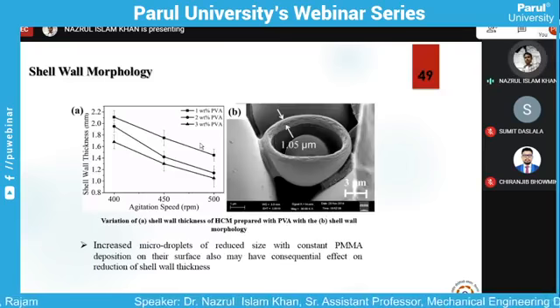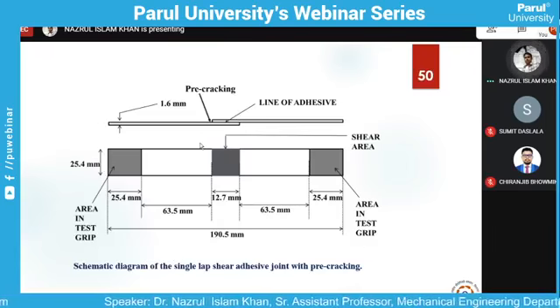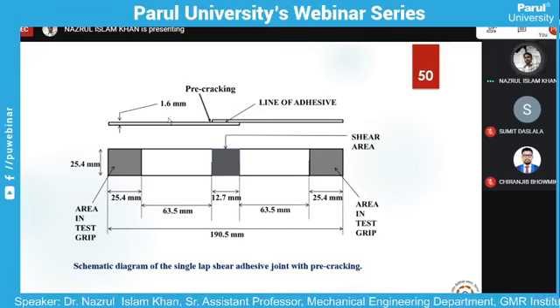I will go a little bit faster. This is the adhesive joint where along this line we applied the smart adhesive on the surface, and once we applied the load, it got broken. Once we took the two substrates and kept them again in the same position and gave a small pressure, it was able to rebond, and again we got the same mechanical properties.